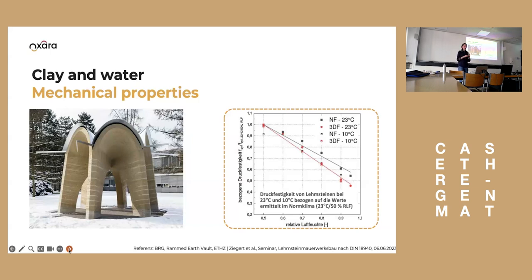So on this figure, on the x-axis, you have the relative humidity inside the room or outside, and on the y-axis, you have the normalized compressive strength. And if we take the compressive strength at 50% relative humidity, on the left side of the figure, as 1 in a normalized strength, you can see how the strength decreases with increasing moisture. And the reason is that the clay-based construction material can absorb the moisture, so it gets adsorbed around these clay particles. But if you have this water adsorbed around the clay particles, it also means that you weaken these capillary bridges that I was showing in the beginning. So you lose the strength when it gets more moist.